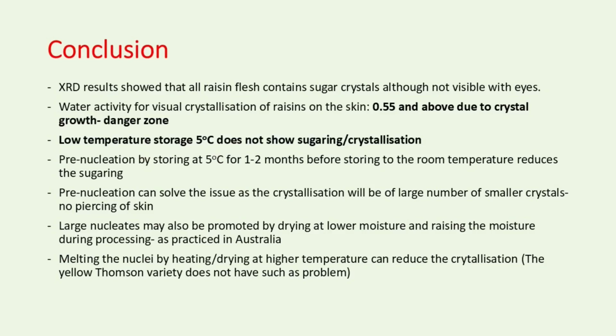So we identified that this is due to temperature fluctuation. Low temperature, 5 degrees, doesn't show sugaring or crystallization on the surface. There are crystals, but they don't appear on the surface. For pre-nucleation, the solution is to pre-nucleate by holding at 5 degrees. Nucleation is very good at that temperature, but it doesn't grow, so that helps to avoid the problem.